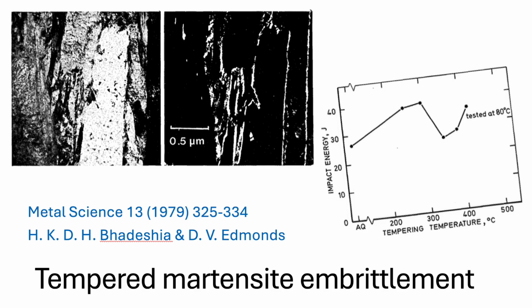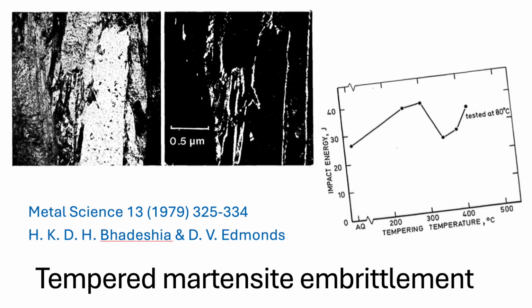Okay, let me try and summarize this for you, the listener. TME, tempered martensite embrittlement, teaches us that tempering steel isn't just a simple linear path to making it stronger and tougher. Definitely not. There's this necessary structural weakness, almost a dangerous window. You have to find the perfect balance. You might want a high tempering temperature overall for strength and toughness, right, but you absolutely have to avoid that critical mid-range around 300 degrees C where these microstructural instabilities kick in, whether from retained austenite or from supersaturated martensite decomposing. Exactly. Because if you temper in that window, you inadvertently create these brittle cementite films. You're essentially building an easy fracture road right through the middle of your supposedly high-strength material.